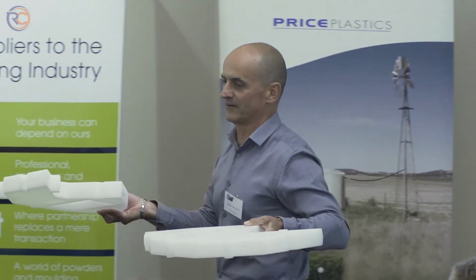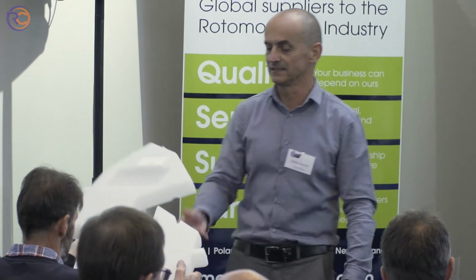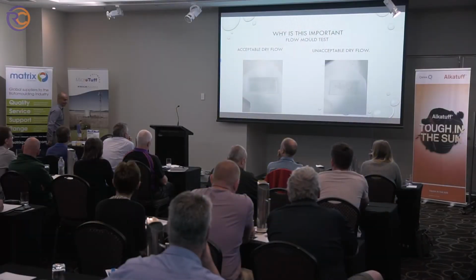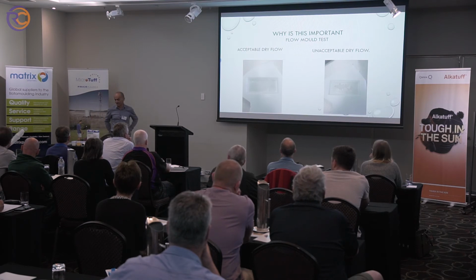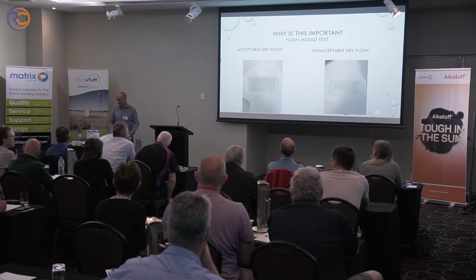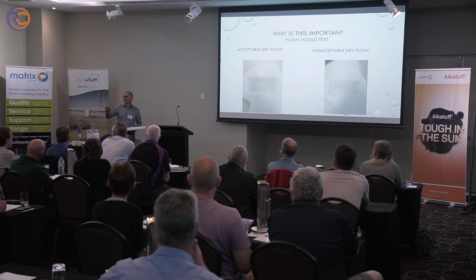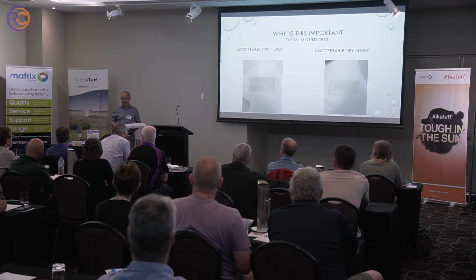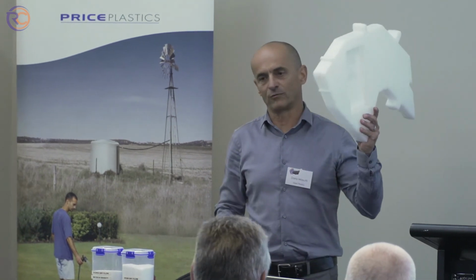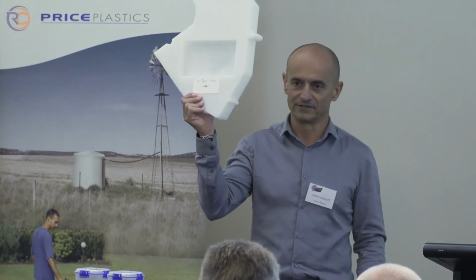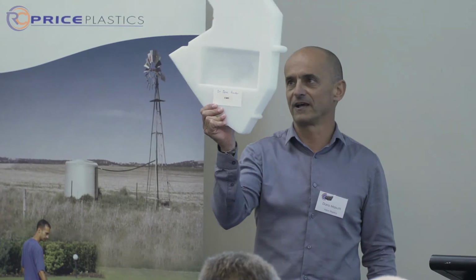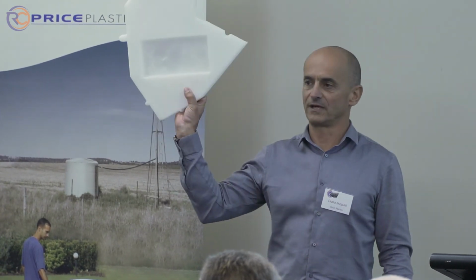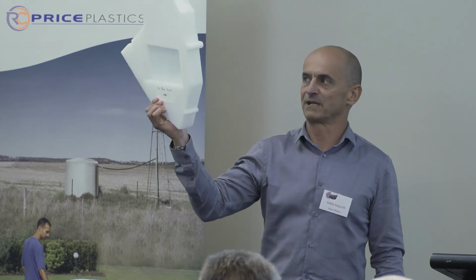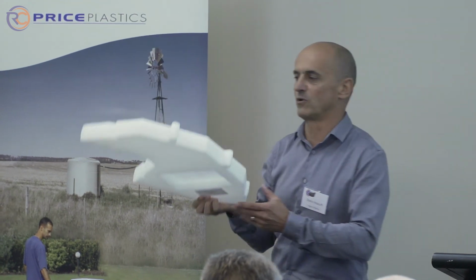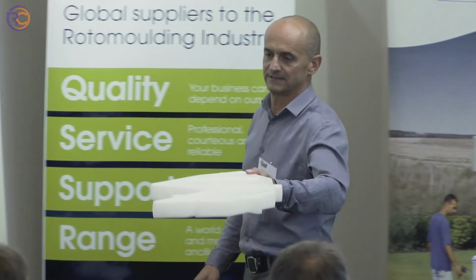And if you have a good look, you'll be able to see in the different areas of this test mould that we use in our R&D to check the powder quality and melt flows and how materials flow. You'll see the different areas. Now, that's exactly the same material, but ground differently. This is material ground well, but with a 3 melt flow. And you can see that the 3 melt flow has done a better job because it's been ground properly, but it still doesn't quite get into the areas that we want it to.